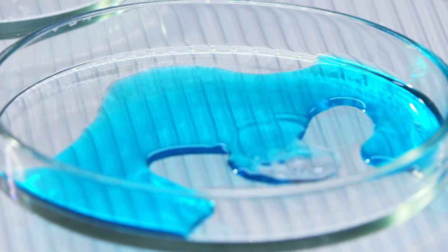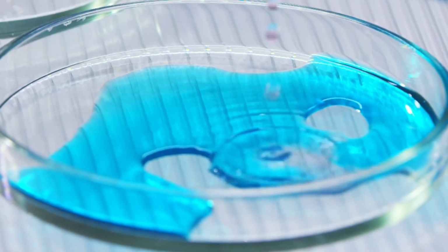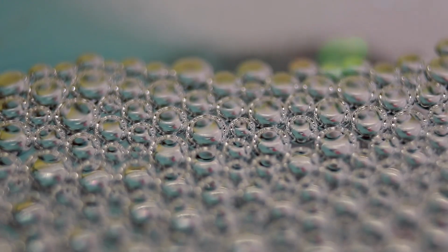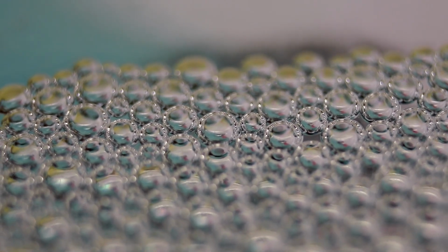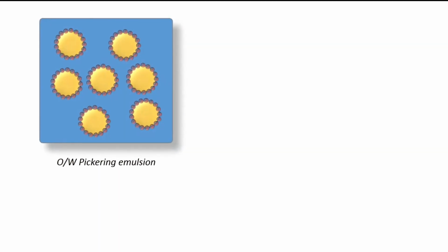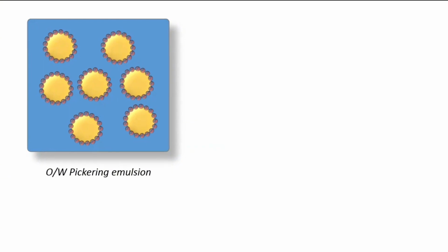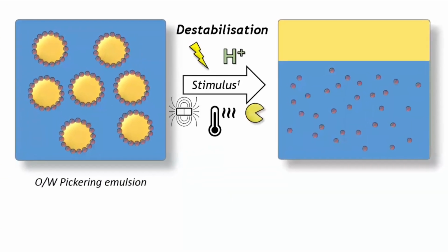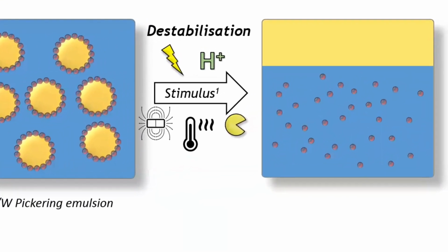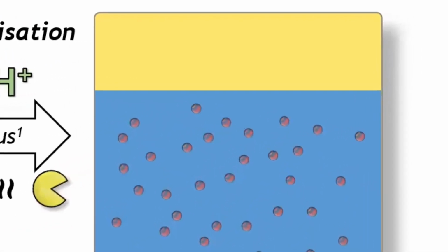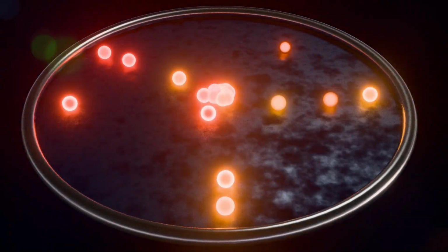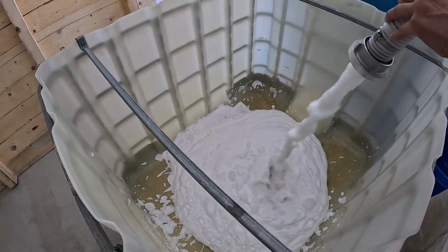The fix came out of surface chemistry, and it is genuinely elegant. Take silica particles at the nanometer scale. Treat the surface so one side of the particle likes water and the other side does not. Those particles migrate on their own to the boundary between air and liquid, and they park there. Once a particle is wedged into that interface, the energy needed to pull it back out is enormous. In practice, it cannot leave.